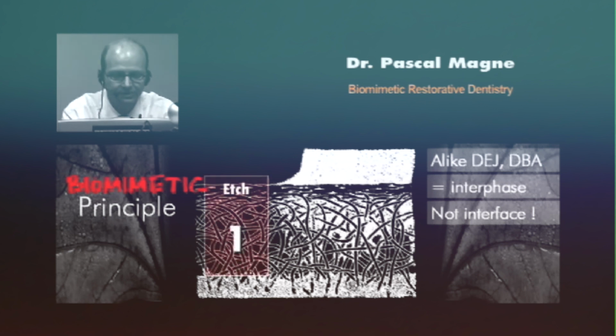And I have to tell you, I could spend an hour on dentin bonding. I'm not going to do that, of course, but I want to tell you that for good dentin bonding, there are 4 steps required. And these 4 steps, you cannot go around. These are separate, let's call them bottles or products, and separate steps that must be applied to dentin. And the first one is etching, demineralizing the collagen surface to obtain this porous layer. The second step is using a primer, a hydrophilic resin that is able to penetrate the demineralized collagen. It has to be hydrophilic. And you cannot mix too much the hydrophilic and the hydrophobic. The hydrophobic is going to be the next layer, which is the bonding resin.